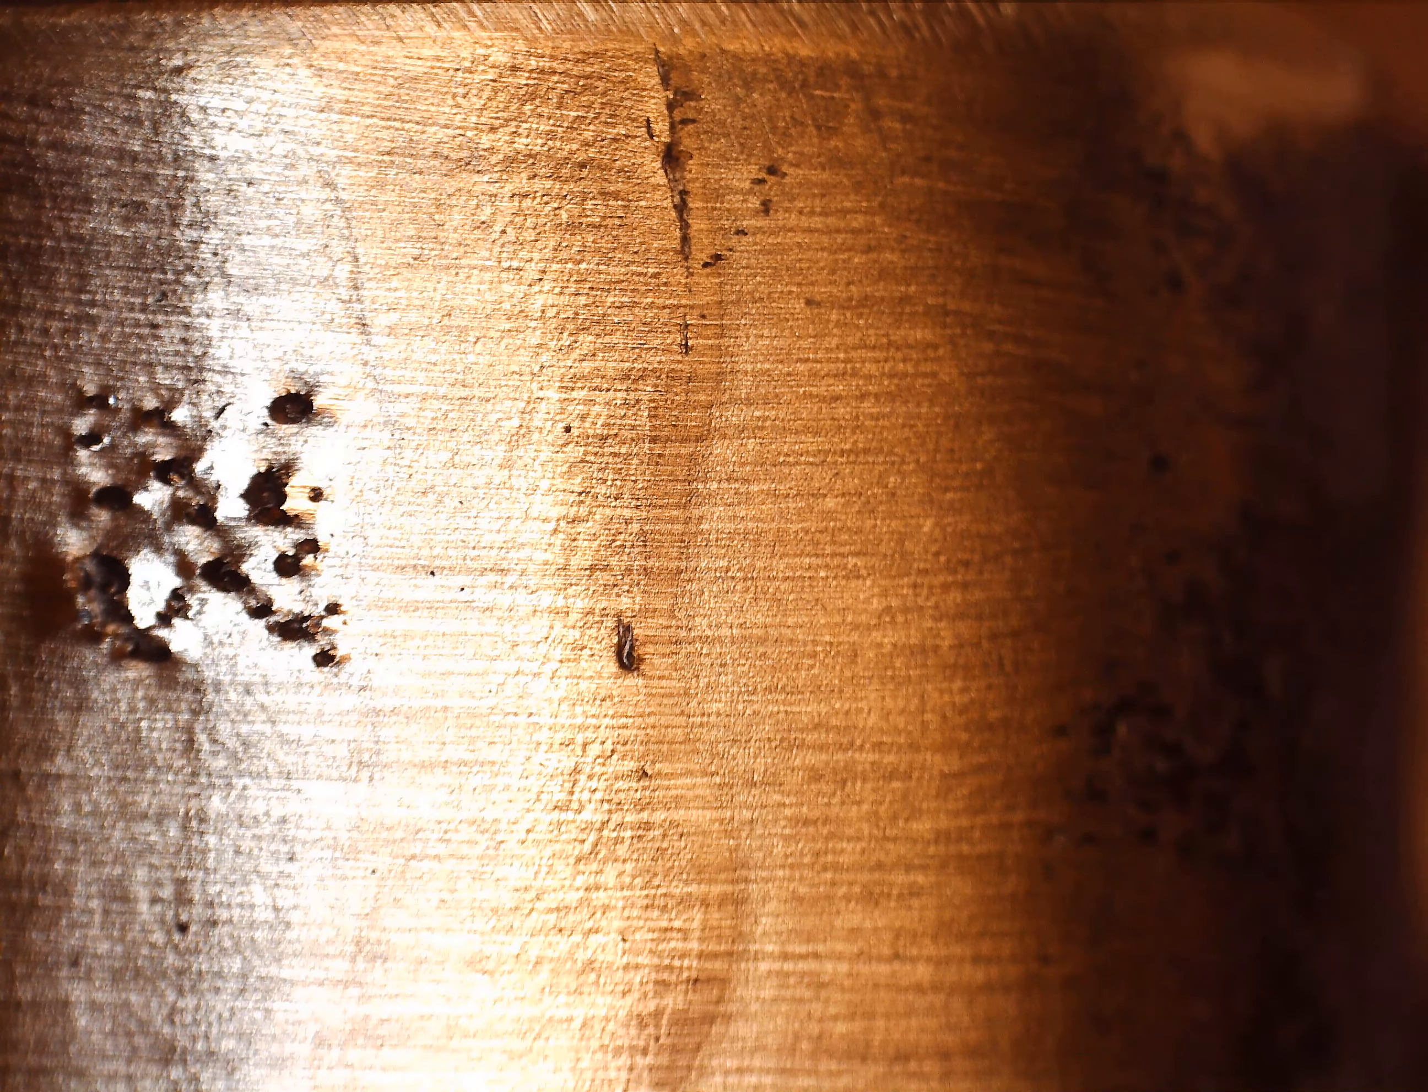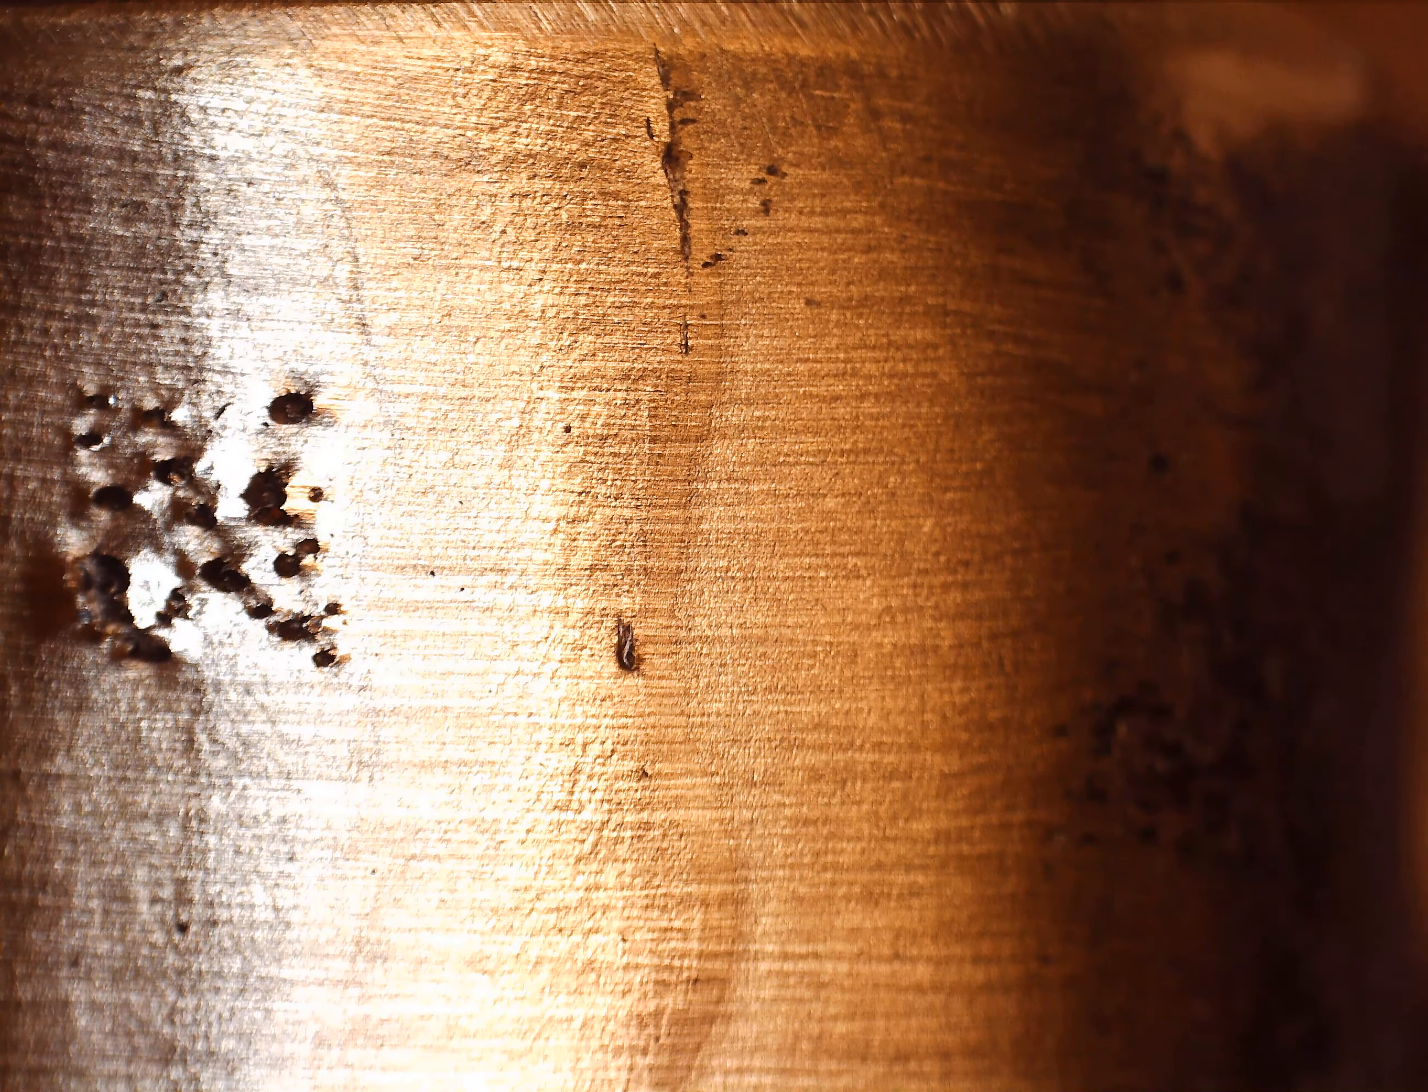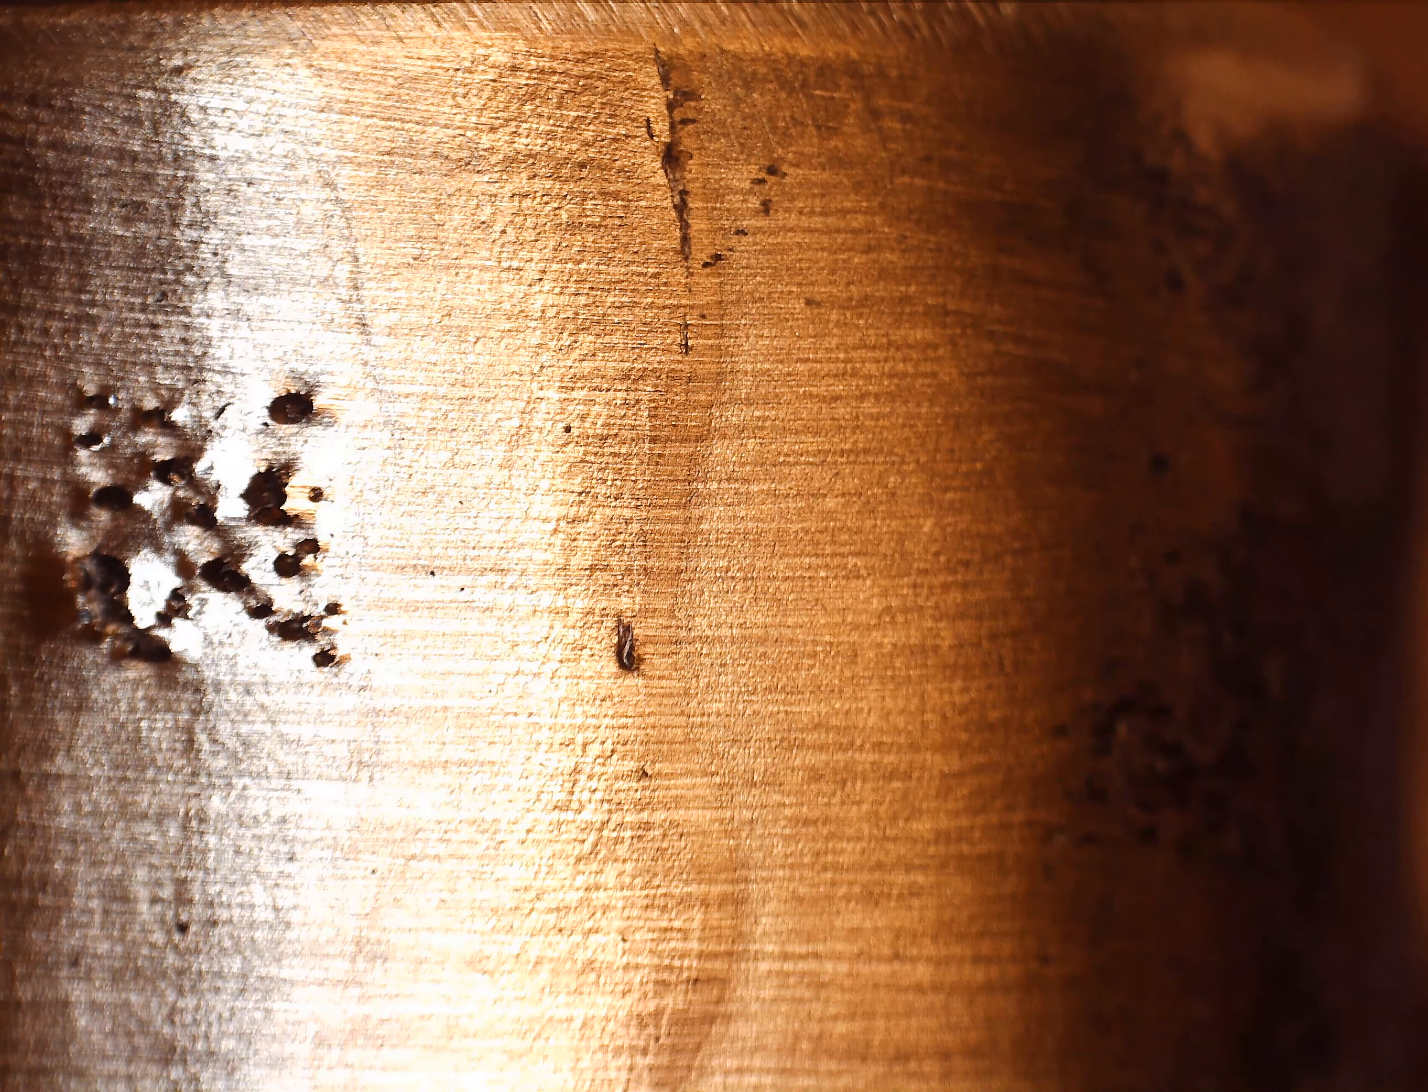Not a big deal, but I would imagine some people look at the picture and say 'oh, that fails.' That little line right there, some folks might even fail, but that's just undercut. We're allowed to have 1/32 inch undercut. The undercut was measured before the specimen was even cut.